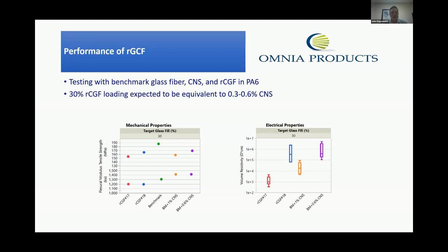So presented here are some of the mechanical properties. You see that there's very little difference in the mechanical properties associated with either the recovered material, the benchmark material, or the glass filled with the CNS product. But interestingly enough, when you look at the electrical properties, you can see that with a 30% glass filled RCGF material, you're approaching very similar properties as with a benchmark glass filled material with the CNS product.